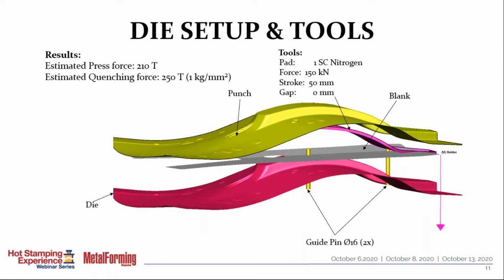We first start, when we look at a part, by evaluating whether we want to hold water or not hold water, and invert it as you see here. And then we try to see if we can crash form it with no control pads or tools. In many cases, that's possible. In other cases, we find that we can't crash form it because of problems not so much with thinning, although sometimes, more often with wrinkling.